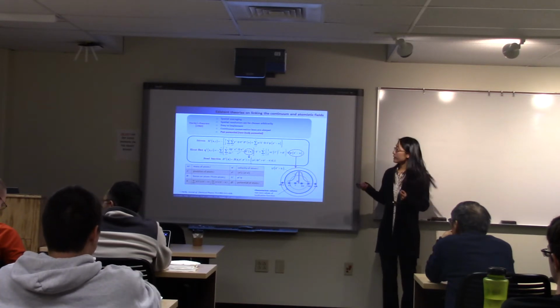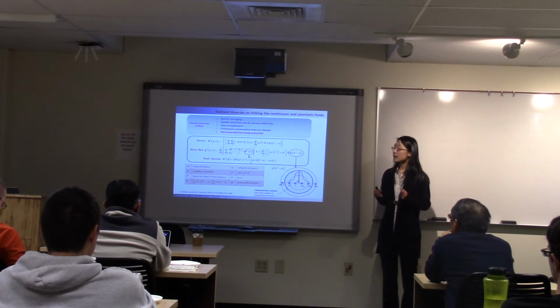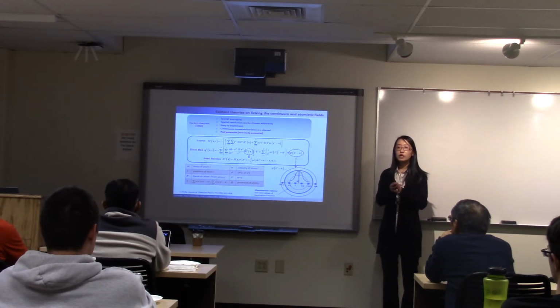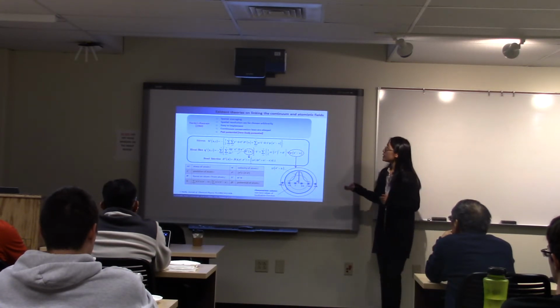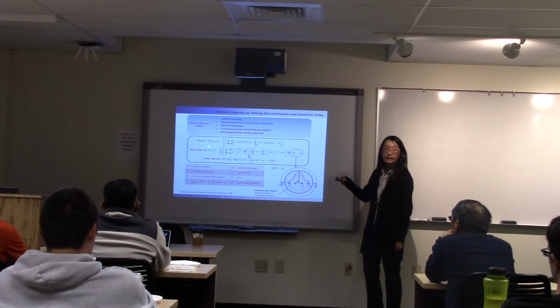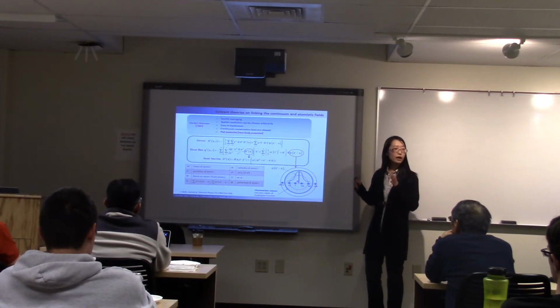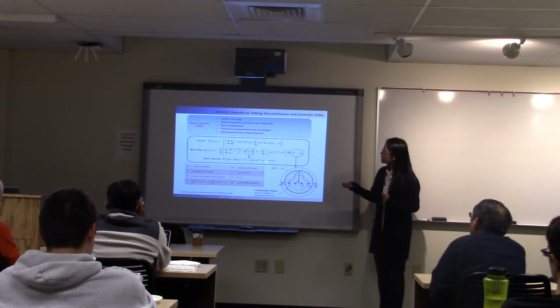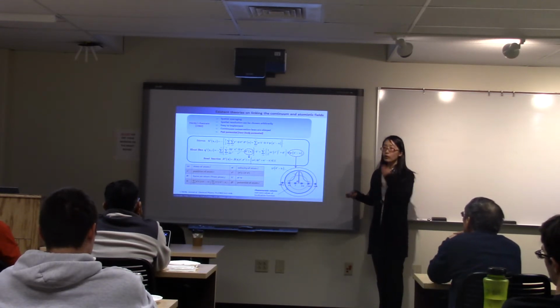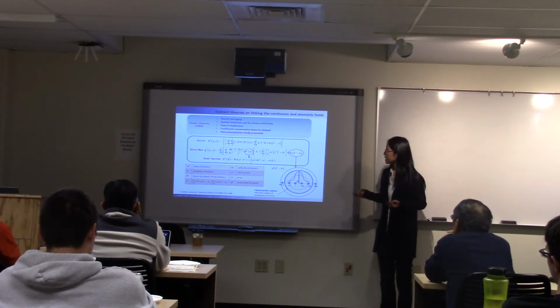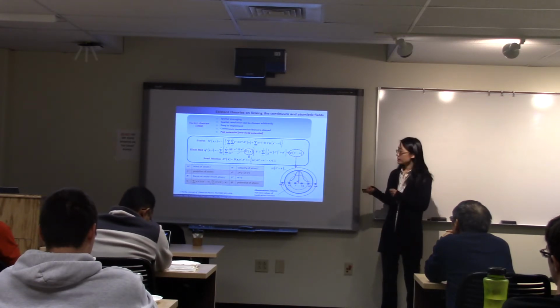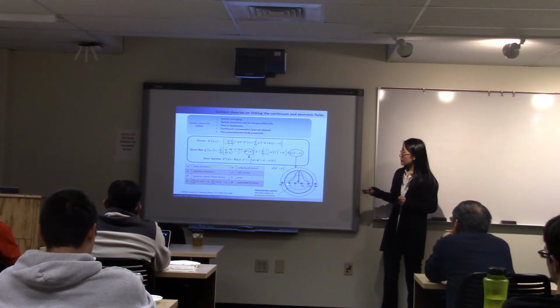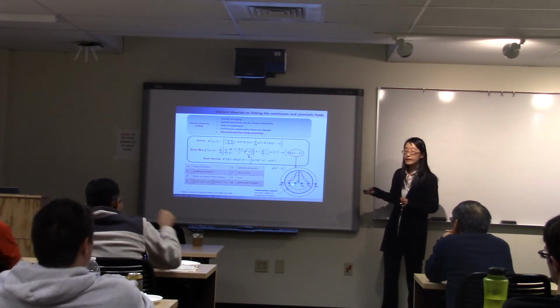Our development is based on the Hardy theorem because it has some advantages compared to other theorems, but it has a limitation: it was developed for the pair potential system. It means that the total energy of the system can be written as a sum over pairs of atoms. Based on Hardy's theorem, the stress and heat flux on the left-hand side can be written in terms of atomic quantities on the right-hand side, where all the needed atomic quantities are listed in the table here. We can easily access them from the MD simulations. And the key in linking atomistic to continuum is this localization function, which gives different weight to those atoms that contribute to the spatial point x in the continuum region.